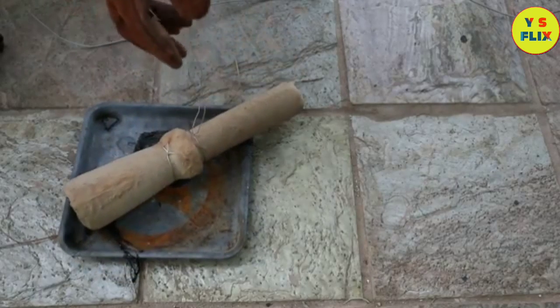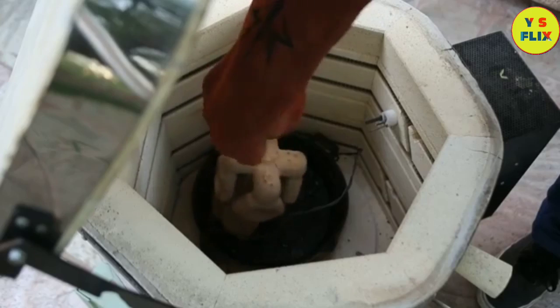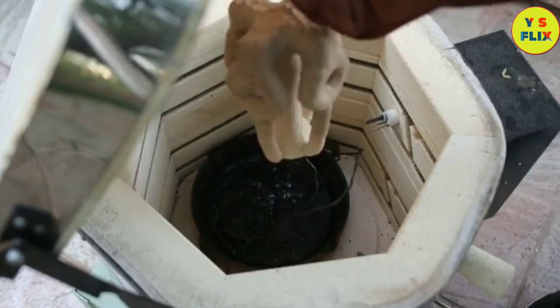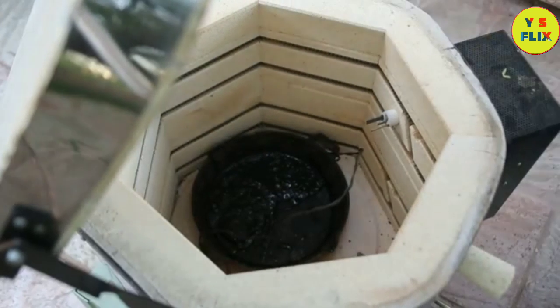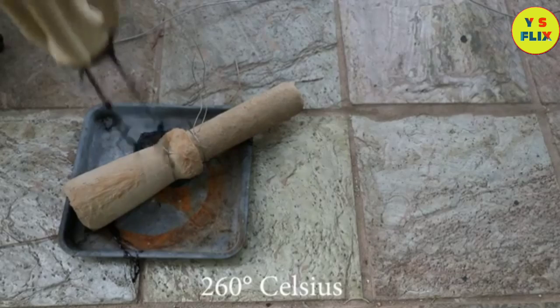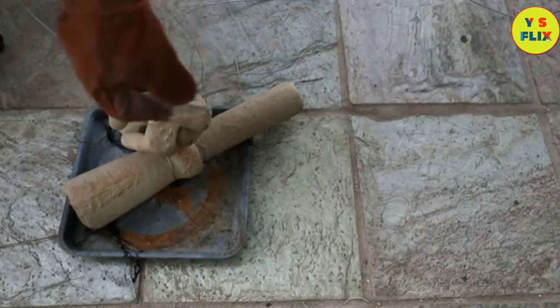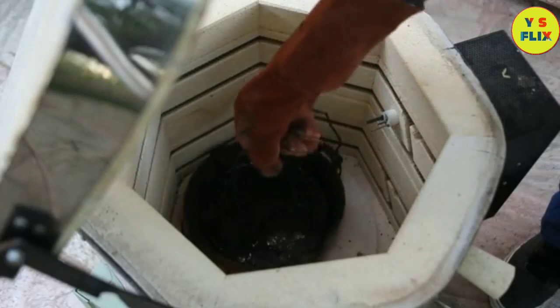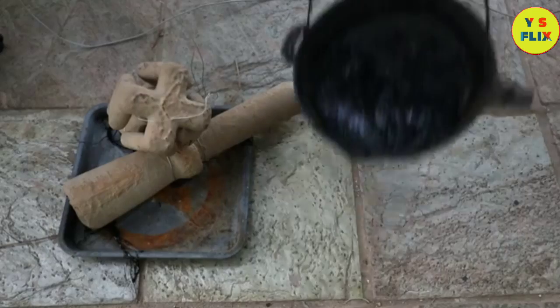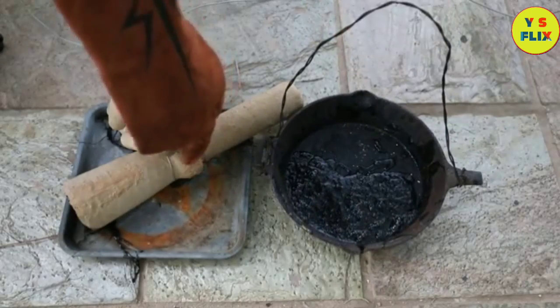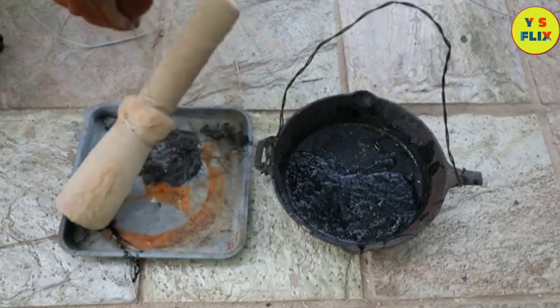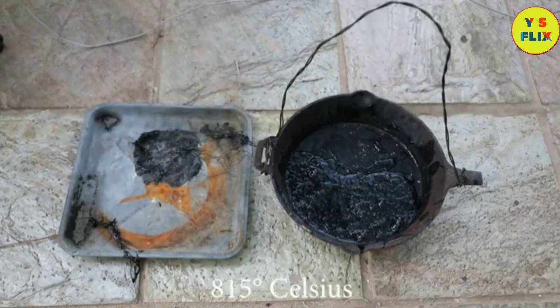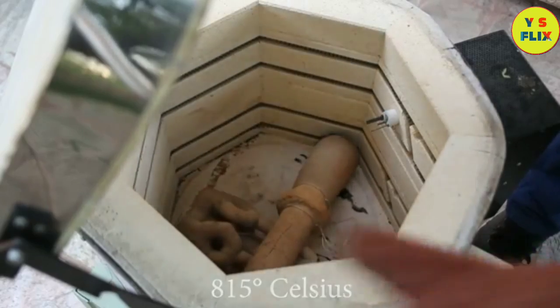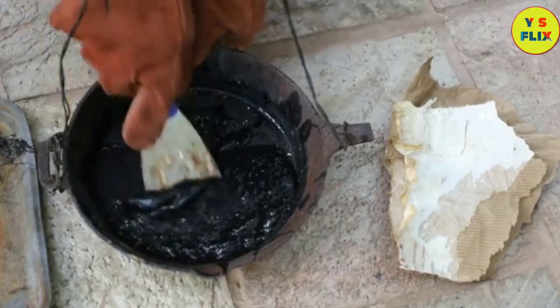It wasn't my goal to just stick these in the kiln and let all the plastic burn away into the atmosphere. So instead, I turned on the kiln and brought up the temperature very slowly to about 500 degrees Fahrenheit, which is the temperature at which the PLA starts to melt out of the shells. When the majority of the plastic had melted out of the shells, I opened the kiln and removed it. Then I cranked up the temperature to around 1500 degrees Fahrenheit. This vitrified the shells, turning them into ceramic that can withstand the temperature of molten metal.